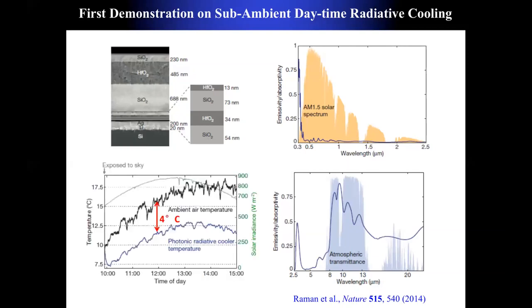And in the end, the result is, just outside, okay? Just putting a piece of material outside, you see the air temperature, and you touch their surface, it's 4 degrees C lower than ambient temperature, okay? Before this paper was published, nobody had ever reported a temperature lower than ambient temperature whenever you put a piece of material outside. And this is very exciting to us, right? This is really eye-opening for us, because usually we go out, we touch anything, it feels hot. And this is the first one that feels cold.